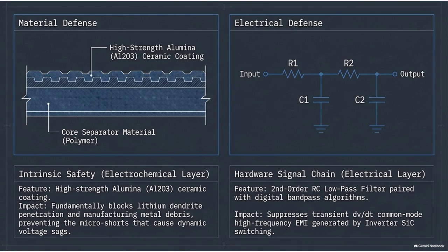Aluminum oxide ceramic. Isn't that the same material class used in, like, ballistic body armor and tank plating? It is, just scaled down to the micrometer level inside the cell. Why is this specific ceramic so effective against a tiny metal needle? Two critical reasons. First is purely mechanical hardness. The ceramic lattice is physically denser and harder than the metallic lithium dendrite or a stray copper shaving.